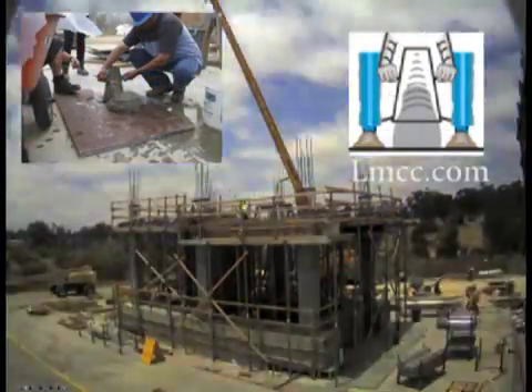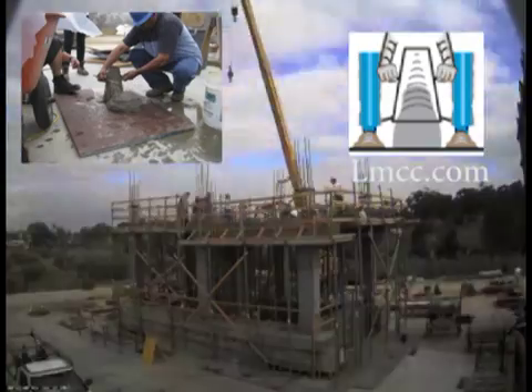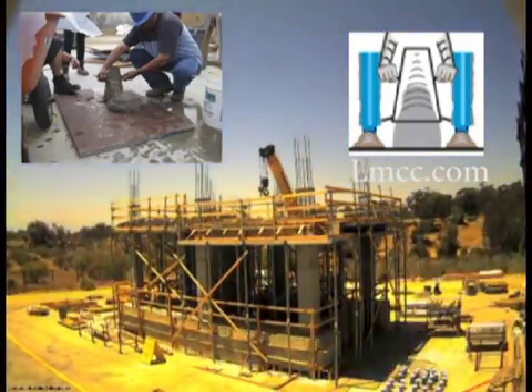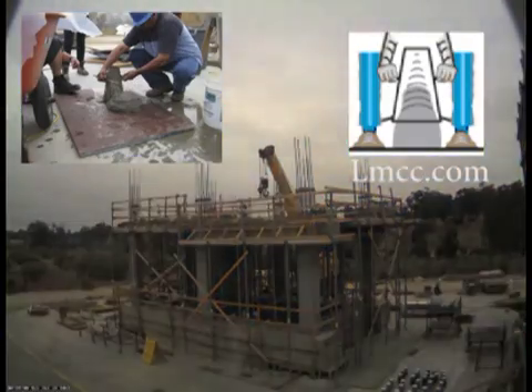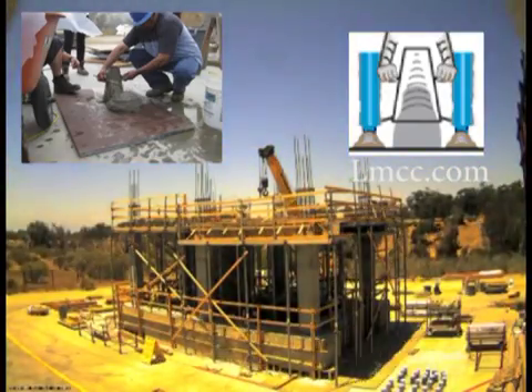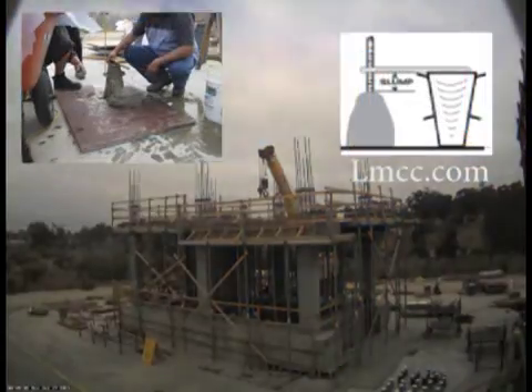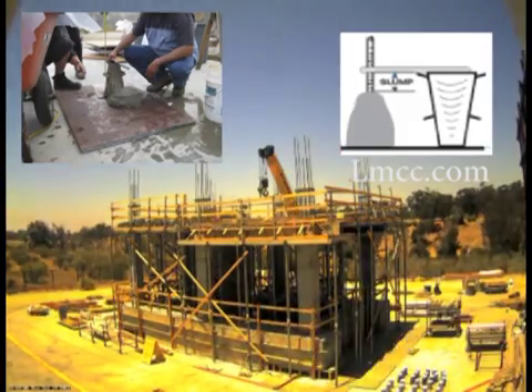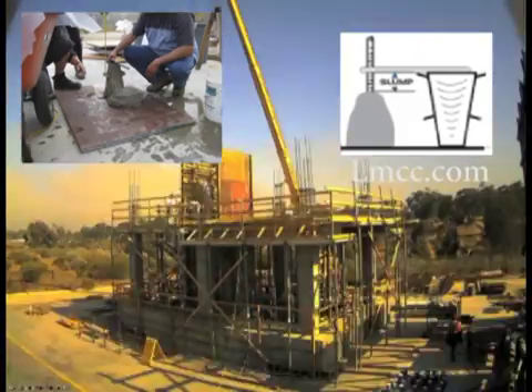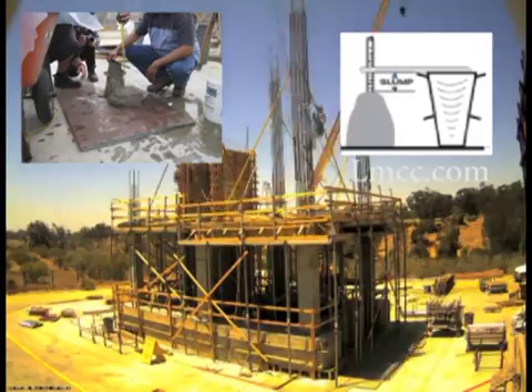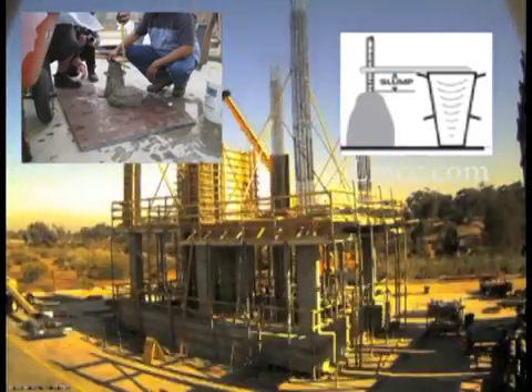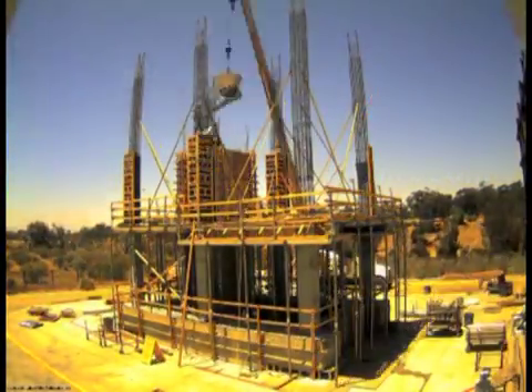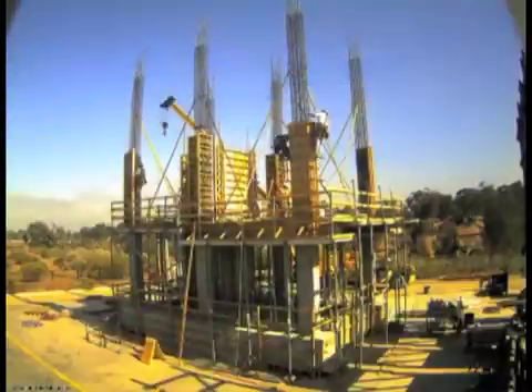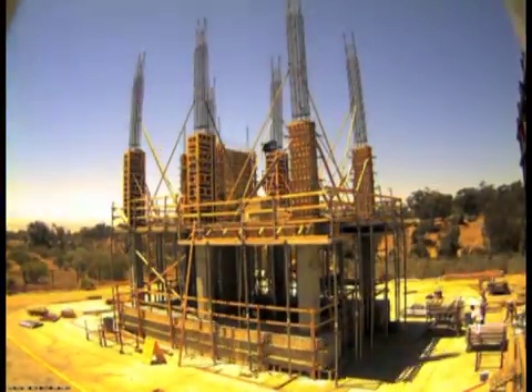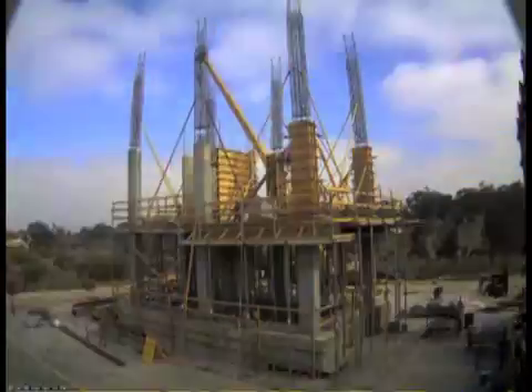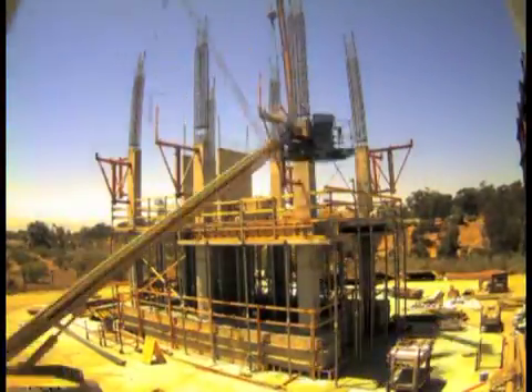The mould is then removed slowly and placed adjacent to the concrete specimen. The free concrete is allowed to slump down under its own gravitational weight. After the slump settles, the metal rod is levelled horizontally on top of the mould, and the distance from the horizontal rod to the top of the concrete is measured. The change in height of the concrete sample is referred to as the slump for that specific batch of mix. The slump measurement is compared with specified values, and a decision is made to accept, modify, or reject the concrete mix before placing the concrete.